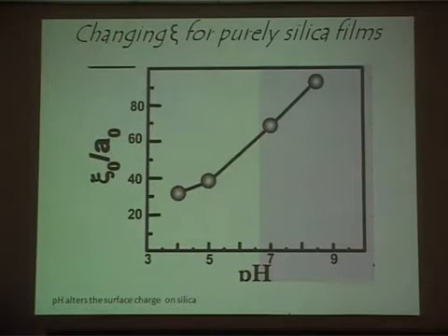You can say, well, I'll not do all of this with polystyrene, but if I can do only with silica. So you can go and choose the system and prepare it at various pHs. And chemists know that if I develop systems at low pH, then bond dissociation at SiOH is lesser. So I basically have lesser amount of covalent bonds. So I will have a weaker structure. So you can do all of that, and then it says that a system which is at a low pH is of low rigidity. So essentially you have a smaller xi naught by A naught. If I develop a system at a high pH, it's of a higher rigidity, and I have a system which has xi naught by A naught, which is large. So essentially, even if you did just with silica particles and not mixed it with polystyrene particles, you still hold the behavior to be same.